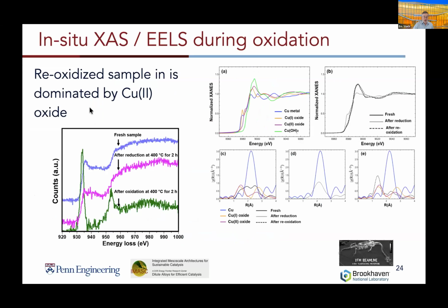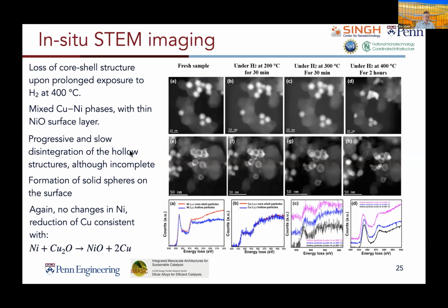If we go back and reoxidize it, we find that we actually get a copper 2 state. And again, that's consistent both in the near edge, where you have a strong pre-peak in the electron energy loss spectroscopy, but also in the X-ray absorption spectroscopy, indicating again that these are showing the same types of information here in the L edge and here in the K edge. And furthermore, if you look at the extended X-ray absorption signals, we again see the presence of the Cu2 oxide after the reoxidation.